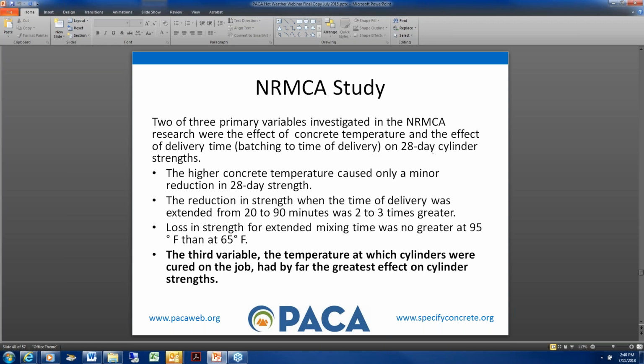Two of the three primary variables investigated were the effect of concrete temperature and the effect of delivery time on 28-day cylinder strength. The higher concrete temperatures caused only a minor reduction in 28-day strength in the study. The reduction in strength when delivery time was extended from 20 to 90 minutes was 2 to 3 times greater - a much greater effect than the higher concrete temperature itself. Loss in strength from extended mixing time was no greater at 95 degrees than at 65 degrees.